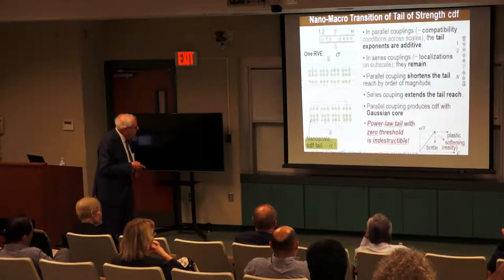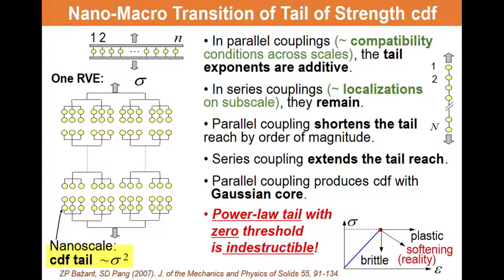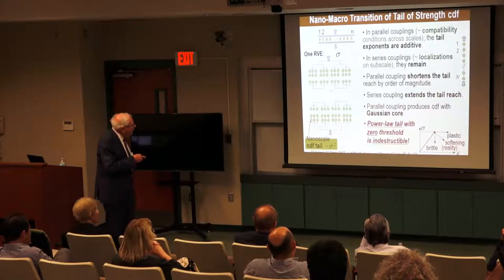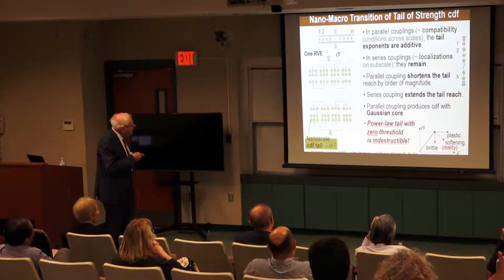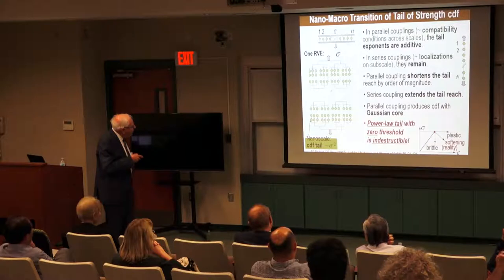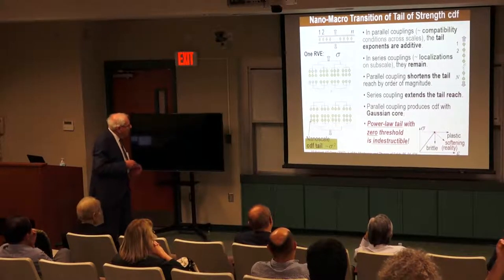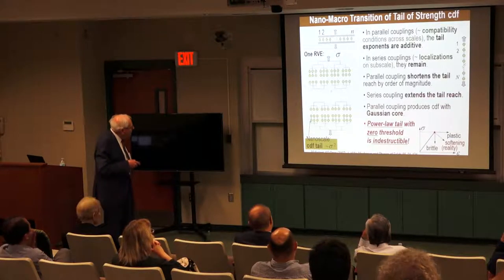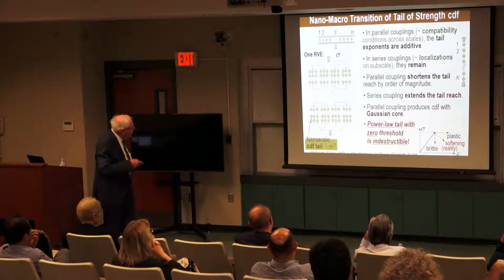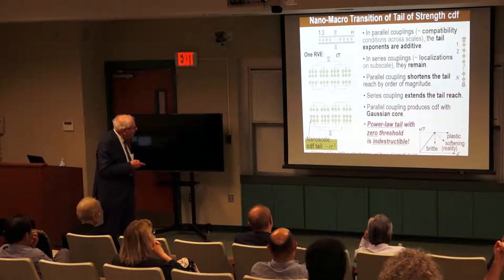Alright, now we consider some models which give this transition. This is one model which we simulated and calculated, with various types of series and parallel couplings. What has been shown, it takes a lot of asymptotic calculations, Laplace transform, but it has been proven that the power law is always preserved by these systems, and in series coupling the exponent is raised but additively, so one element here has tail exponent 2, 2 have 4, 3 have 6 and so forth. In a chain the power law is preserved, but the penetration of the power law tail changes in the opposite way, and the only possible way to explain what we see is alternating series and parallel connections. Many connections in series, many in parallel, and that's how we can explain what we see on a larger scale.